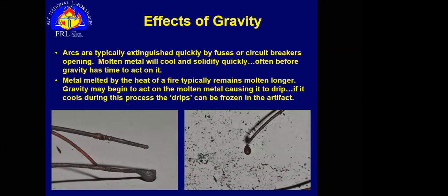As opposed to fire impingement, where we're dealing with high temperatures on the order of minutes, we now have time for gravity to start acting on that molten material. So you can see on these pictures, we're starting to get flow of the molten material. We're getting narrow areas like on the right picture, we've got our nice little thinned out area. I'm trying to draw with the trackpad, so give me some slack here. But you can see where all that material is starting to flow just because time is allowing this stuff to be acted on by gravity.